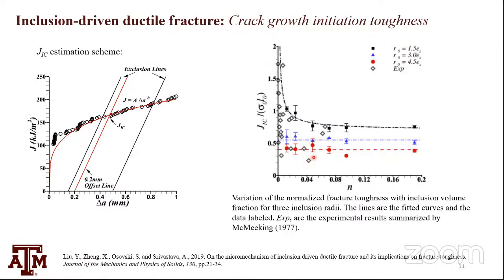And here is a set of experimental results from multiple ductile materials. These are not for one set of material. Our model wasn't calibrated at all to match any one of these. This could be just serendipitous, but it is exciting to show that the results predicted by the calculation show realistic comparison with experiments. These experimental results were summarized in one of the papers by Professor McMeeking. So we can get nice, realistic inclusion-driven fracture simulation.